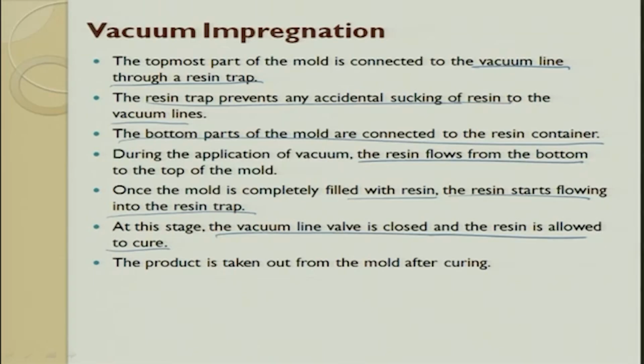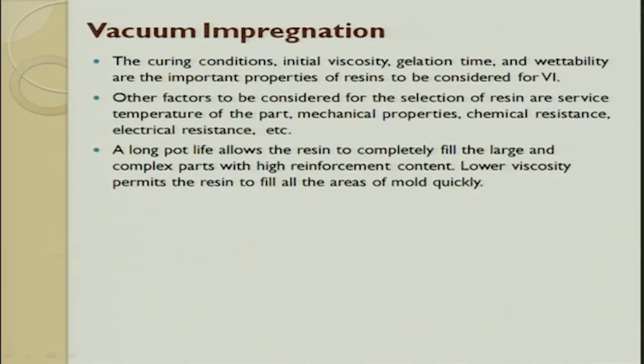And here, as you know very well, I told you, for curing to happen, one is pressure, the other one is temperature. So, you maintain a certain temperature, you allow it to cure, or you can also do it at room temperature if you want. Room temperature slowly cures. If you want accelerated curing, you do it. So, this process is called the vacuum impregnation process, wherein by applying vacuum the resin is impregnated into the preform. In the curing conditions, initial viscosity, gelation time, and wettability are the important parameters of the resin which help in VI. We have already studied that the resin viscosity plays a role, gelation time is over a period of time when it starts curing, and wettability is the fiber and the polymer trying to attract each other, join each other to form a strong bonding.